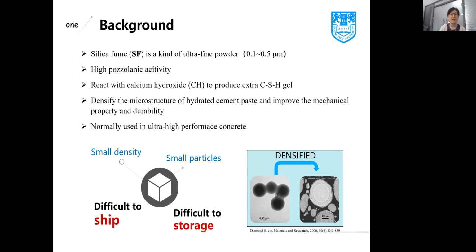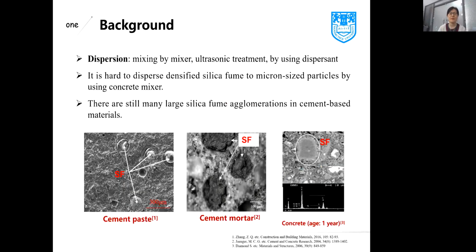Just as it has small density and small particles, it's difficult to ship and also difficult to store. So in the market, it is normally densified. There are many methods to disperse densified silica fume in the using process, such as mixing by mixer, ultrasonic treatment, or using dispersant. But it's hard to disperse densified silica fume to micron-sized particles by using a concrete mixer. There are still many large silica fume agglomerations in cement-based materials.